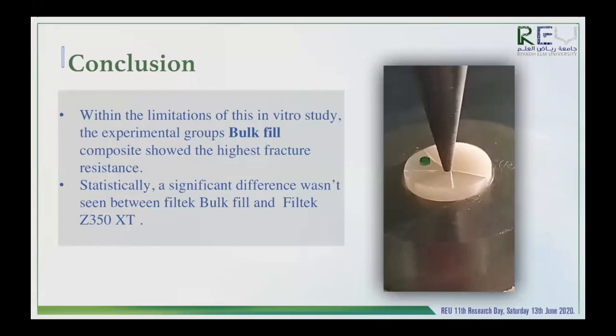Conclusion: within the limitation of our study, the experimental group's bulk fill composite showed the highest fracture resistance. Statistically, a significant difference wasn't seen between the Filtek bulk fill and Filtek Z350 XT.